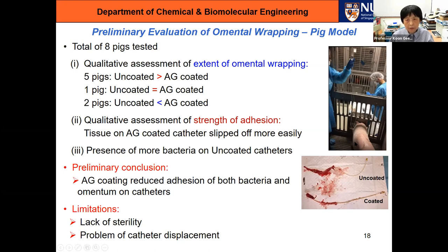One is the lack of sterility. We know that patients will try to keep their catheters clean, not like what we see in the pigs. And then also a problem of catheter displacement, meaning that we cannot leave the catheter in there for too long because the pigs get very irritated with the catheters in there and will do everything to try to get rid of them. So the period of testing is actually only 28 days.